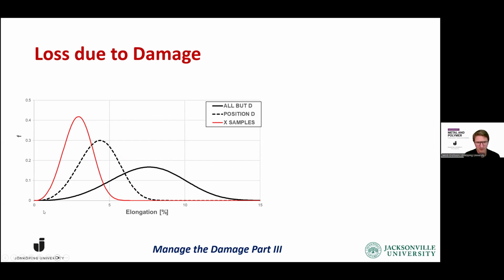But let's also take a look at the samples that I mentioned where we have clear visible porosity. On top of this hidden damage, we also have the visible porosity. And that's the red curve. That's the X samples, so that's the samples with pores. Position D are samples without pores, but with a lot of hidden damage. And the general curve is the one for all the other locations.